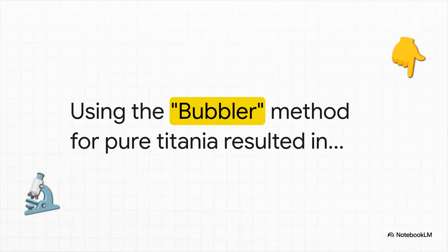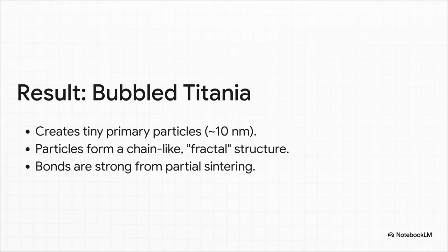So first, let's look at our starting point, our control group. When they made just plain old titania using that gentler bubbler method, they got a very specific kind of particle structure. The bubbler method made these teensy tiny primary particles, only about 10 nanometers wide. And these little guys would link up together into these long, chain-like structures. The bonds between them were really strong, almost like they had partially melted and fused together.